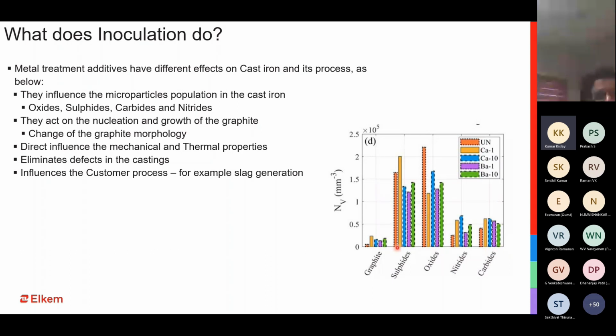And what does it do? It creates those small microparticles, basically the nucleating sites on which the graphite precipitates or the growth happens. So what are these microparticles? These microparticles can be the sulfides, oxides, nitrides, even carbides in some cases, which then act as a friendly site on which the growth would happen. So they act on the nucleation and the growth of the graphite.